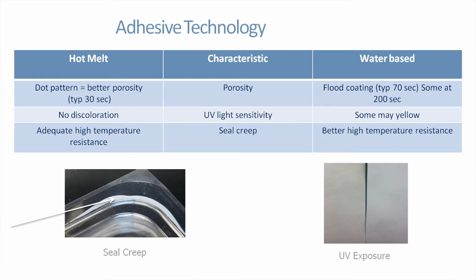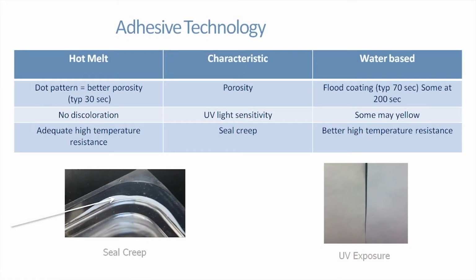And then a yellowing factor, be careful if you're using a water-based adhesive coating. Some of them have a tendency to yellow over time and with exposure to UV. It's a cosmetic problem, it's not a functional problem, it's not a patient safety problem, but just beware of that. That picture kind of shows it, but it's a slight yellowing that can occur.